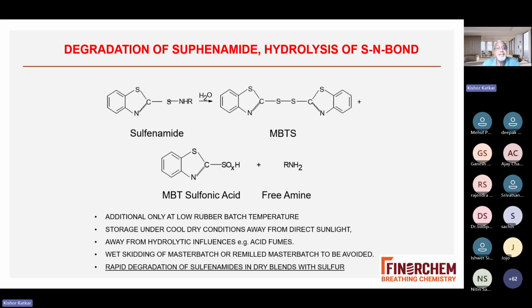Now I was talking about the degradation of sulfenamide. Though sulfenamides are good, they are the condensation products of MBT and different amines. But during high ambient temperature, or during exposure to high temperature during mixing, or during high humidity also, the sulfenamide reverts back to MBTS and amine. That is called hydrolysis. So you require reasonably fresh sulfenamides.